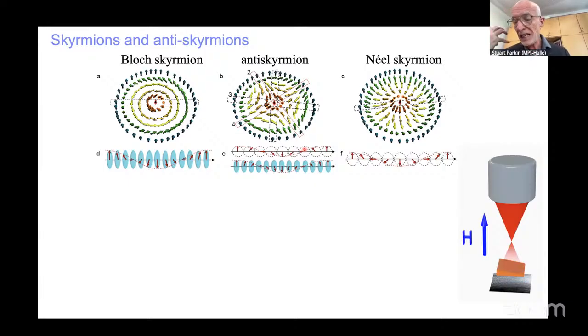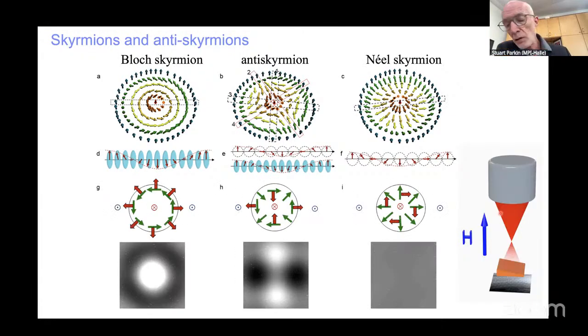In this case, we take a single crystal material. We cut out of the single crystal a very thin layer, which is electron transparent, using focused ion beam milling. And we pass a high energy electron beam through this thin membrane. And the electrons are deflected through Lorentz forces induced by the component of the magnetization in the plane of this lamella. And then you can calculate what you expect to see.